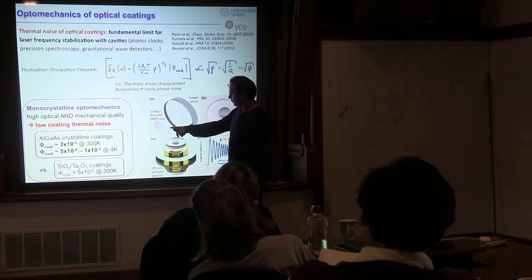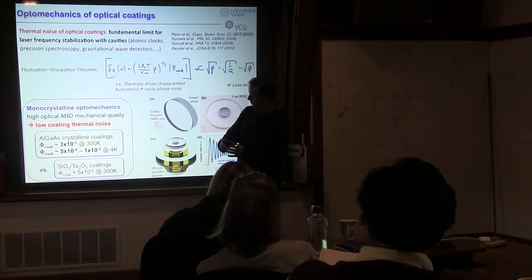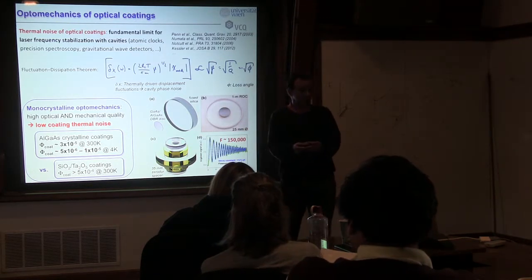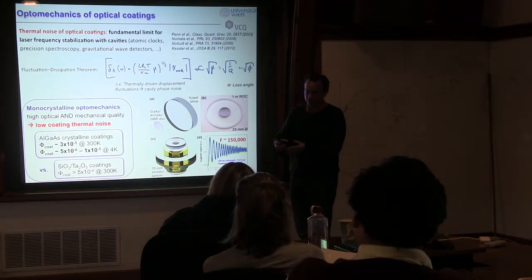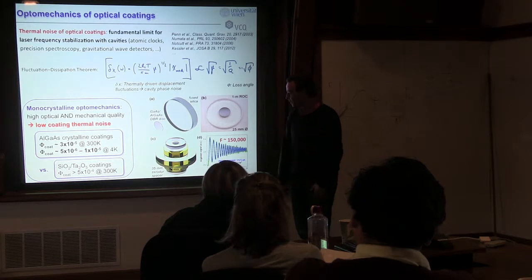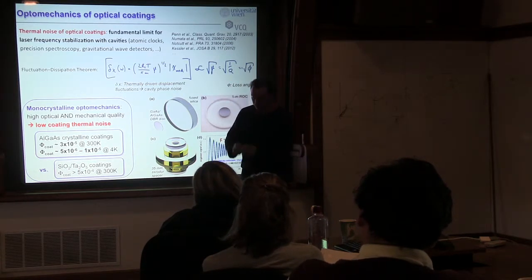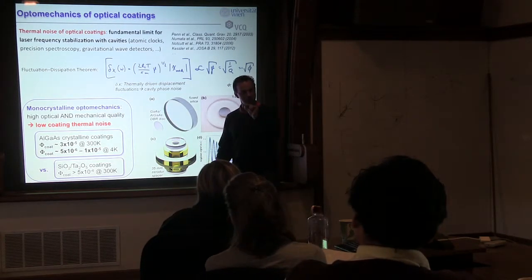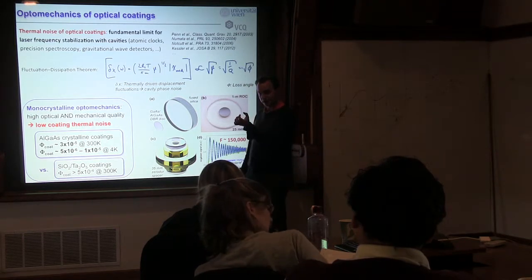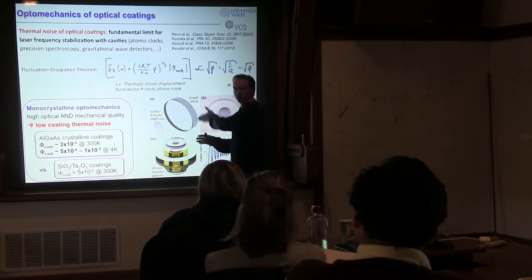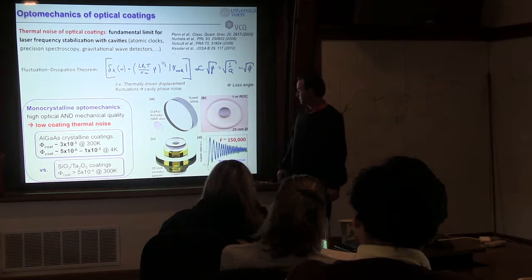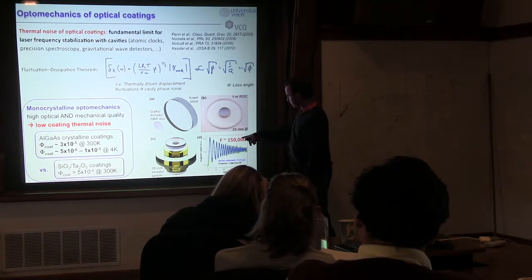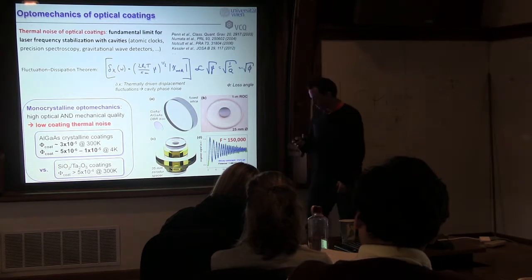It turns out you can actually now grow your single crystal coating on top of gallium arsenide, for example. So you have to grow it on a single crystal wafer. Of course, otherwise you lose because you need epitaxy, you need lattice match and so on for the growth. Then you can remove it from the substrate. Basically, you have a freestanding disk now of a centimeter, like a 6 micron thick AlGaAs Bragg coating, and that you can now bond onto a curved substrate. Right, so onto a curved glass substrate, for example. Then you can put it on a spacer, build a cavity out of that, right? And so the first cavity that we did had a finesse of 150,000, so that was quite good.